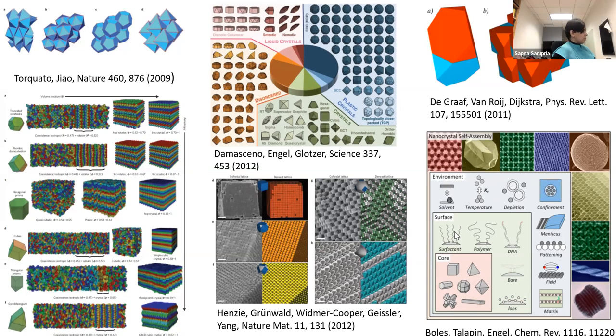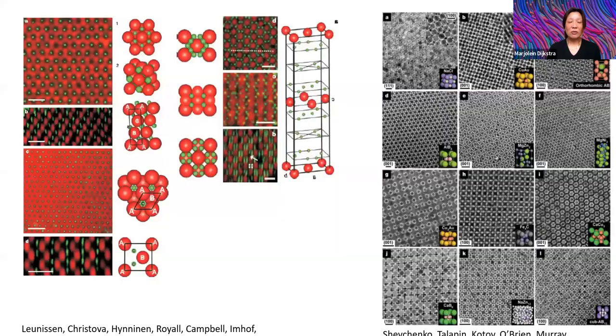Yes. So we can also change the surface and coat them with surfactants, polymers, or DNA. And so one can also change the interactions by just using these surface functionalizations. One can also play with the interactions of the particles. For instance, one can look at oppositely charged particles, positively charged big particles together with negatively charged small particles, and that gives us a whole zoo of different ionic colloidal crystals. And this is done for big colloids, but one can also do that for nanoparticle systems.